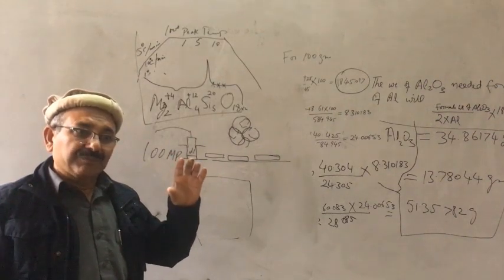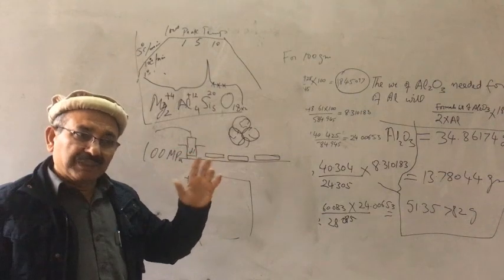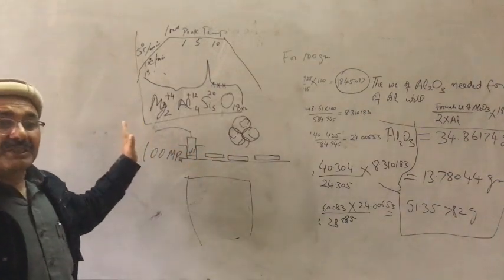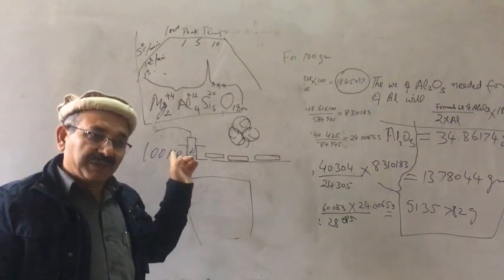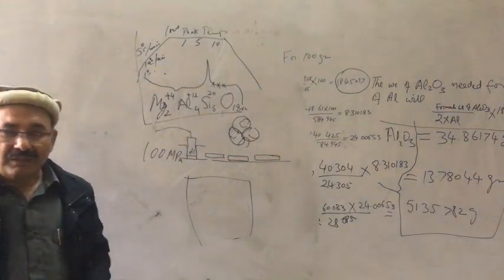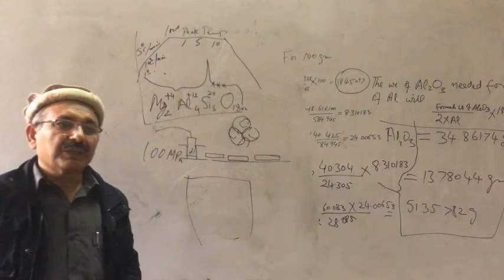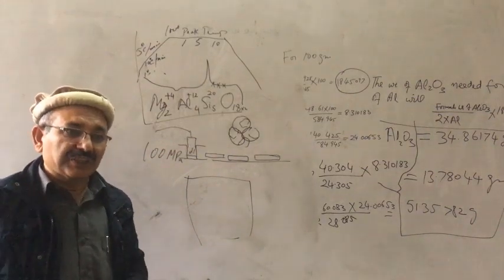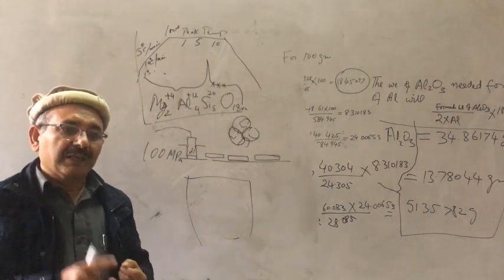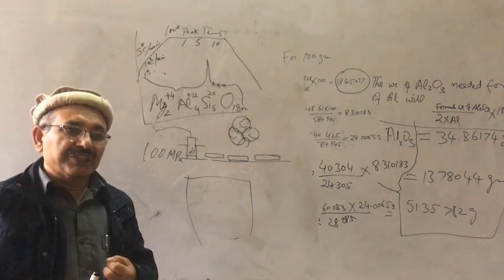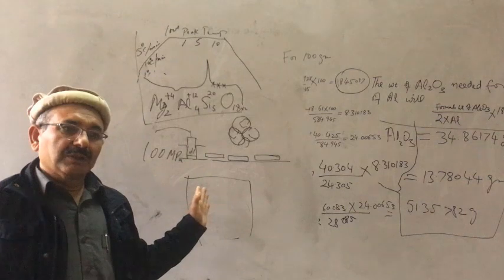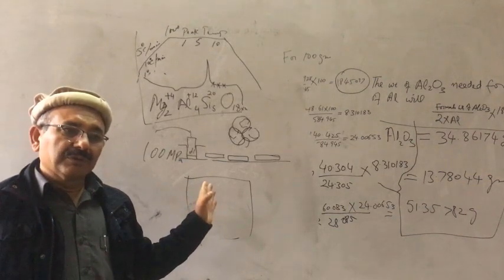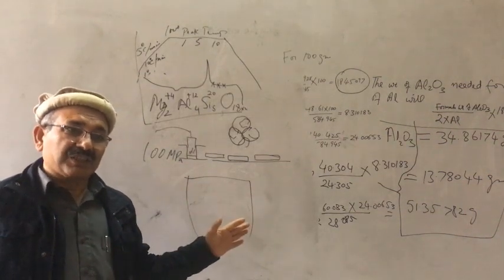The ionic radii of the two must be within 15%, otherwise it will form another phase. It will not be that phase. So if you follow these conditions, the charge neutrality and the radii matching, then you will make a compound which will have the same basic crystal structure.